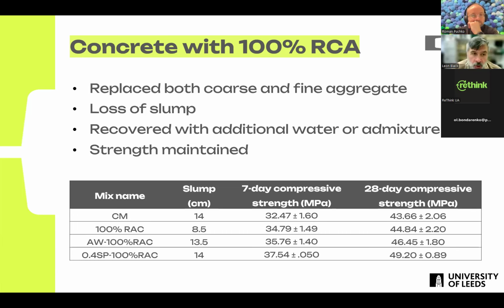Because of the adhered mortar, there was a loss in slump. Okay, so the concrete didn't flow quite as well. If we go from our control mix with a slump of 140 millimeters, it dropped to 85 millimeters. But we could add a bit of additional water to that and it corrected for the slump. Or we could add a superplasticizer and that brought the slump back to where it should be.